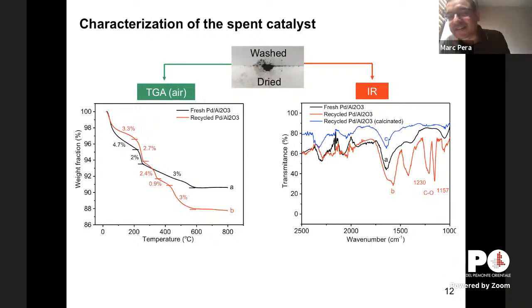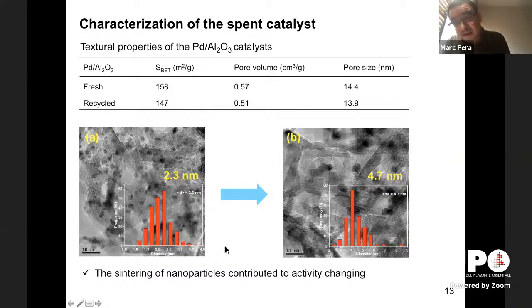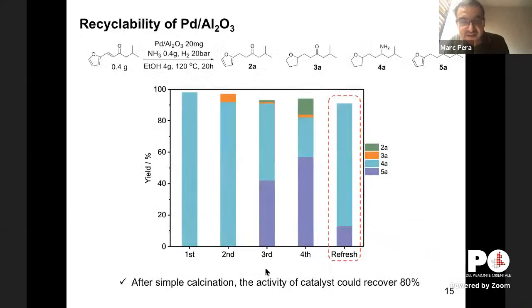Unavoidably, this kind of catalyst has some formation of oligomers during the reaction. You can see very well by TGA and infrared the presence of these oligomers on the catalyst. In particular for palladium, we will always see some sintering. Amines promote sintering of palladium. So even you can see things like this.